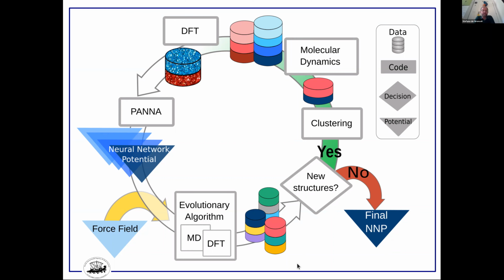Suppose that you have some force field, a reasonable one or an unreasonable one. You generate the data by molecular dynamics or by any other method. You may have a number of configurations that you start from. Using these configurations, you calculate the energy of each configuration by DFT, and then you have a bunch of configurations.